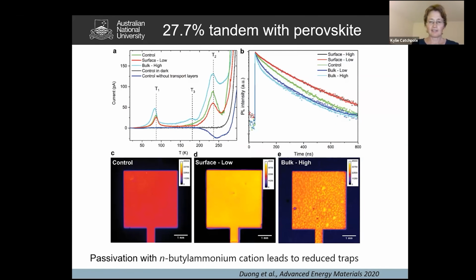And again, the key to this, in this case, also was the passivation. So we used passivation with the N-butyl ammonium cation. And what you can see here is that we compared putting this material in the bulk or on the surface. You can see from the photoluminescence images that you have a very high photoluminescence when the material is on the surface. And you can also see in the top left that we have lower traps from those current measurements as a function of temperature. So you can see particularly the red case is reduced, showing that the surface low concentration shows definitely reduced traps compared to the control case.